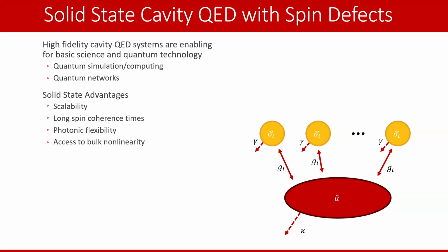We're interested in controlling the phase of this interaction, G. We're interested in controlling the loss rates from the cavity mode out to other systems or out to the environment. And while we can't really control the individual loss rates inside the spin defect centers, the color centers themselves, we can choose color centers that have level structures and rates that are more interesting. But this, of course, requires controlling all of this.